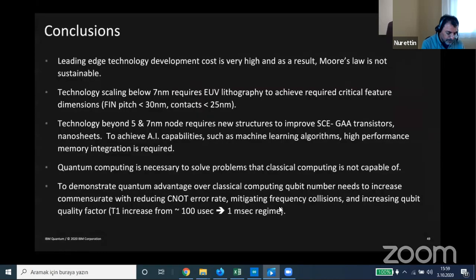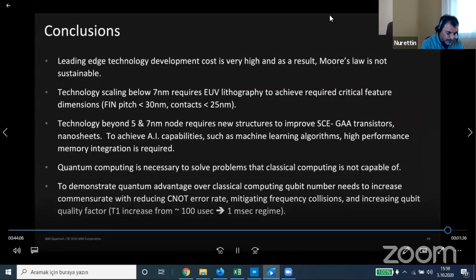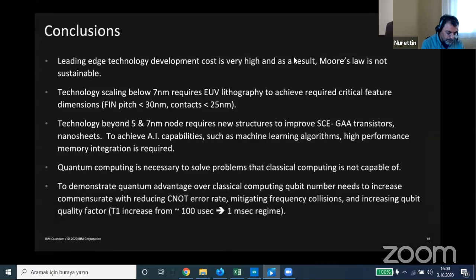So in conclusion, leading edge technology development cost is very high. As a result, Moore's law is not sustainable. Scaling below 7 nanometer requires EUV lithography to achieve the required critical feature dimensions. For a fin technology, that would mean scaling the pitch below 30 nanometers. It would also require contacts to the source drain that are less than 25 nanometers, which would result in very high contact resistance. So the contact resistance is a very big challenge to achieve performance.